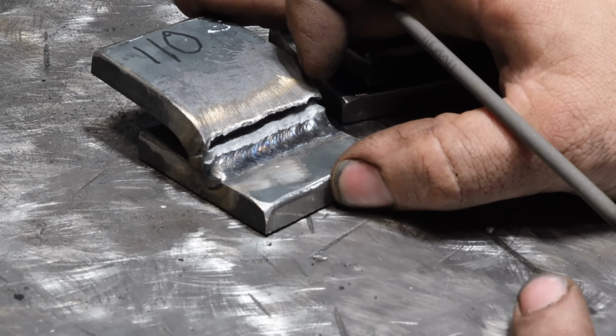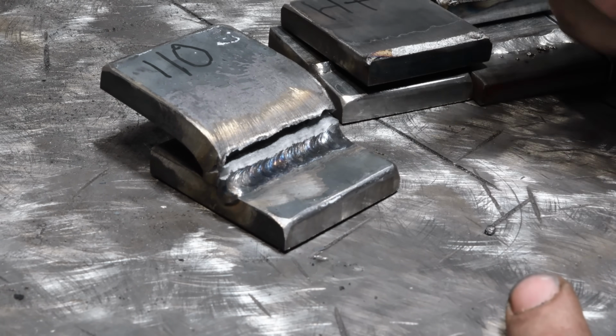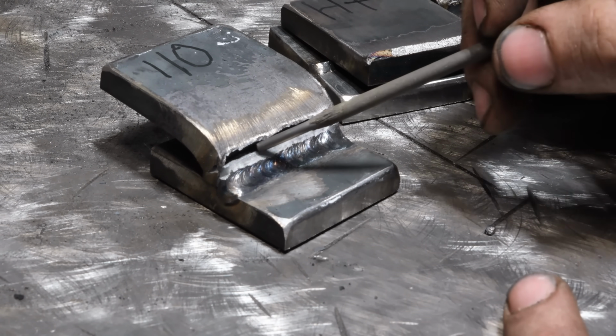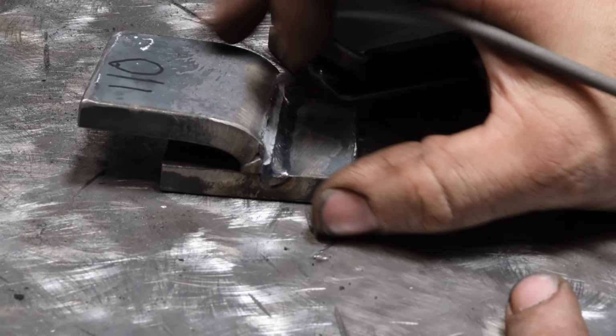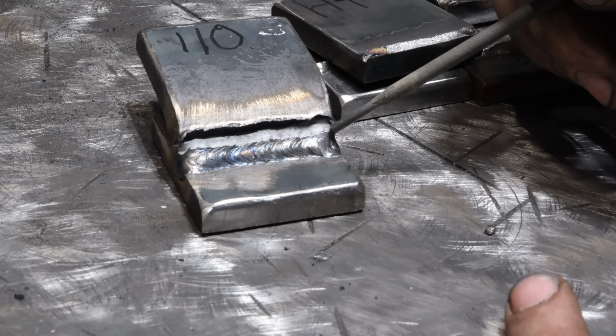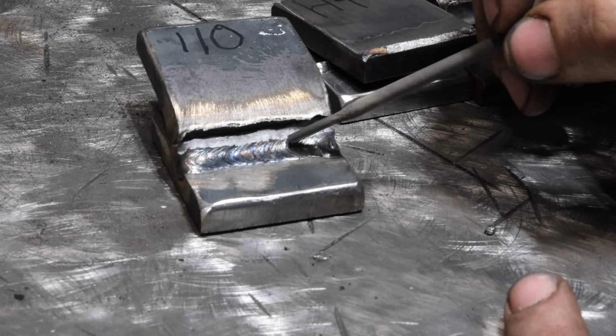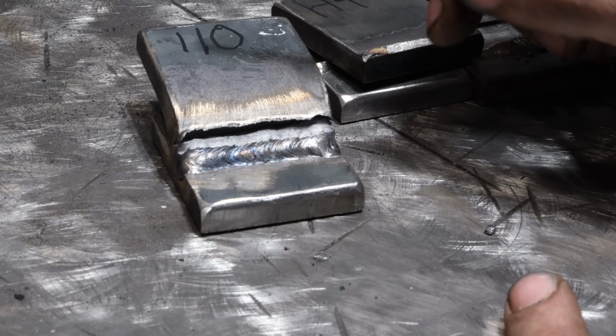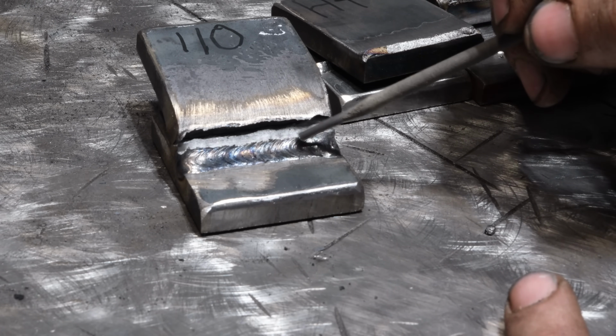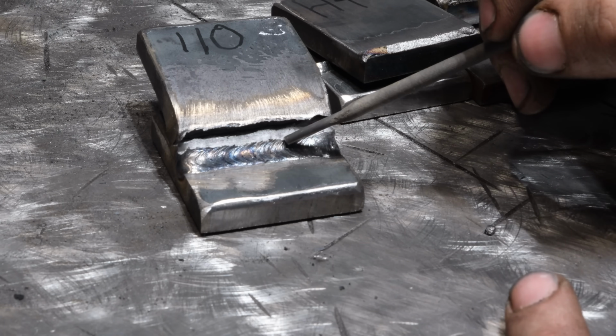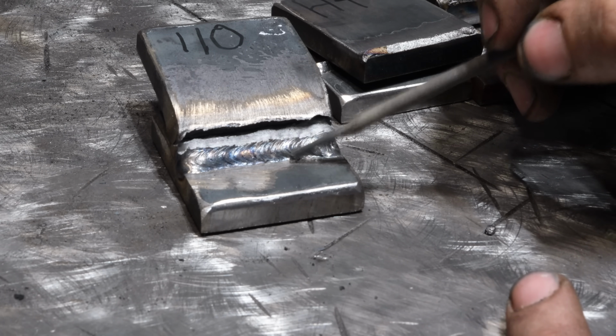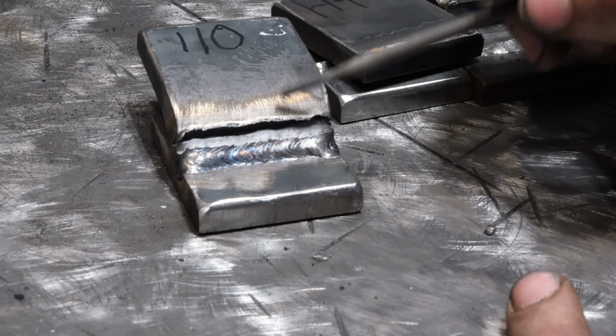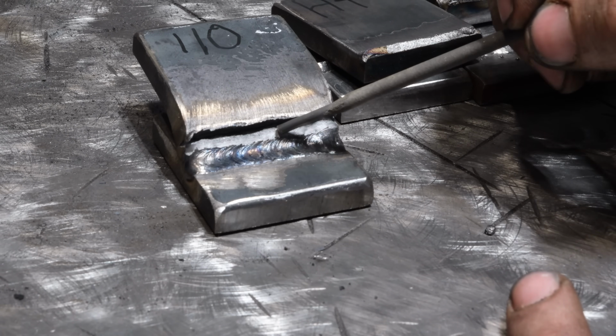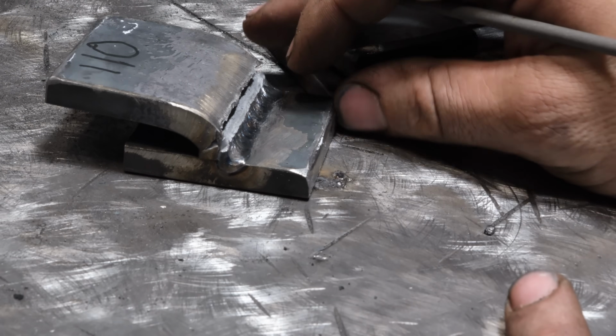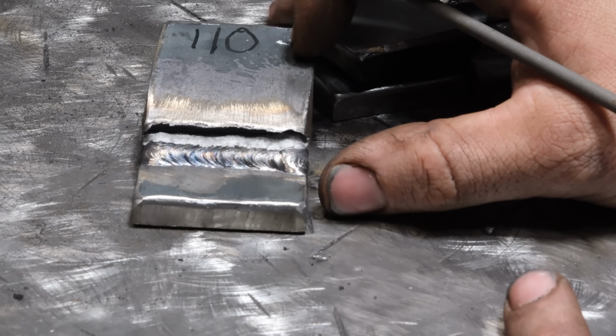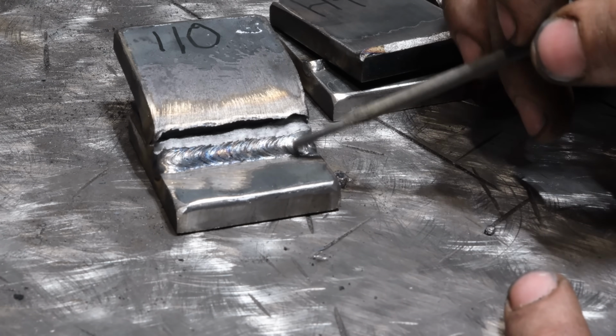Now the 11018, this is kind of interesting. So the plate itself tore. I've seen this before, but the way that it tore is a little bit different. And I would have to take a guess, and an educated one at that, and say what's going on here is the angle that these plates are at when I put all that pressure on it, and the lack of any kind of stretch on this weld basically put all of the force right on the toe, and it just ripped the plate through. So I saw that with 6011 before, and not nearly at the pressure that this was at. So I think it's, like I said, just that the weld doesn't give.